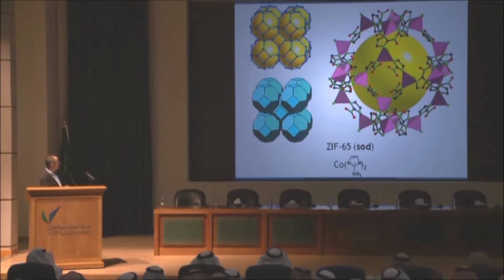This is sodalite, which is a silicate that's not porous and is now made porous by the expansion of the link from oxygen to imidazolate. So here's ZIFs. Here's another new class of materials that fundamentally is different than MOFs. And these, again, these are very stable in strong bases and in water. One of these is one of the most hydrophobic material ever known, and it's already being applied for hydrocarbon separation by BASF and made in multi-ton quantities.